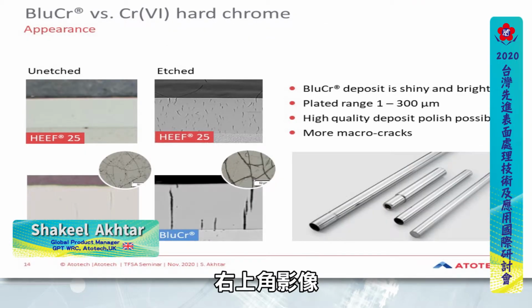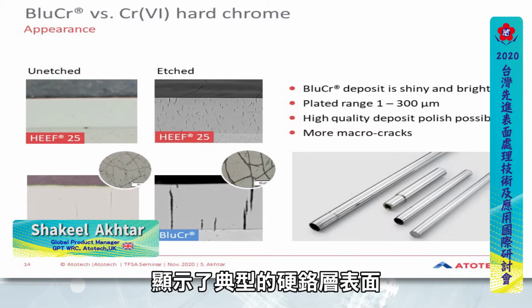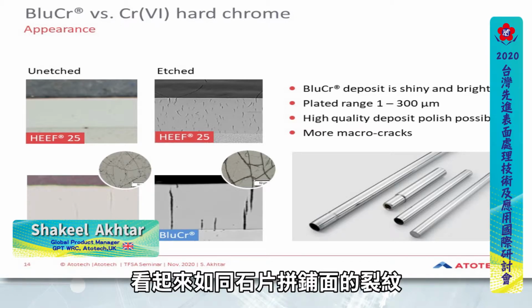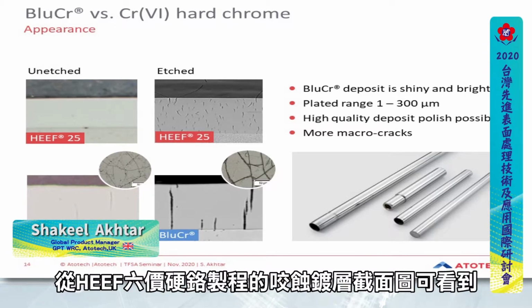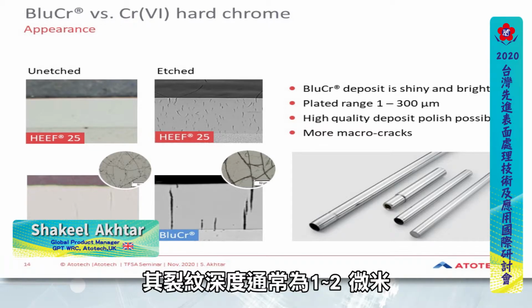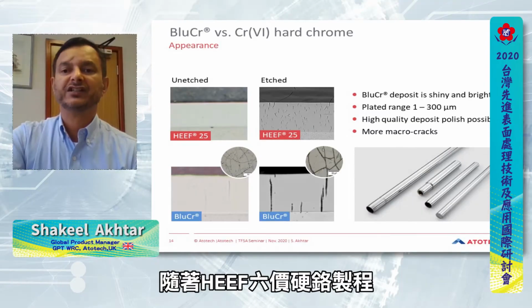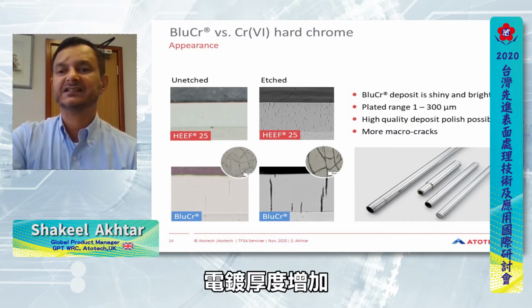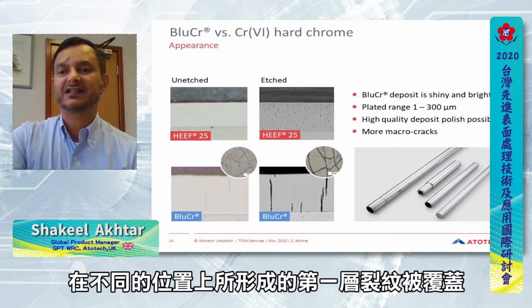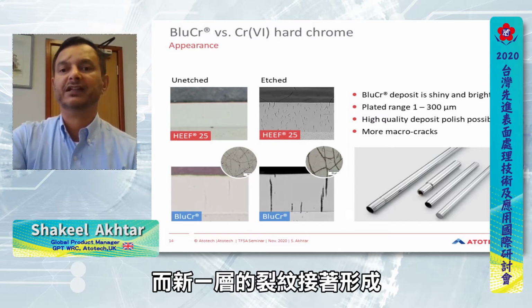This stress forces the deposit to crack and thereby release the stress. The image on the top right-hand corner shows the surface of a typical chrome plated layer with a crazy paving like pattern of cracks. With the hexavalent process, the crack depth is usually 1 to 2 microns and can be seen in the etched cross-section of the HEEF process. During the plating, as the thickness increases, the first set of cracks that form get covered and new cracks form in different locations within the deposit.